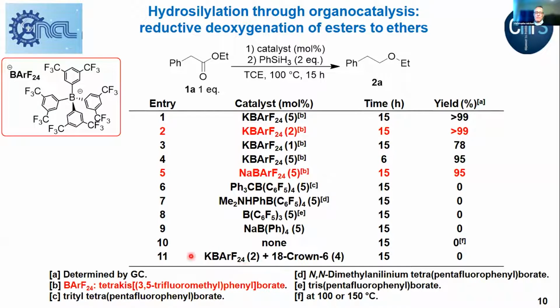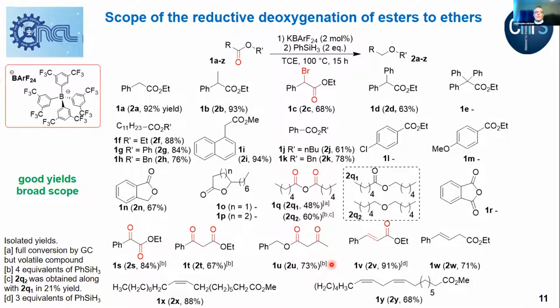We evidenced the key role of the potassium in this reaction by trapping it with 18-crown-6 ether. As a result, the reaction was completely quenched while using this crown ether, which trapped the potassium completely. Looking at the scope of the reductive deoxygenation of esters to ethers, we could evidence a broad reactivity with various alkylated or arylated esters. The reaction has some limitations. Alpha-brominated esters could not be kept; we had debromination while also reducing the carbonyl. Sterically hindered substrates displayed no reactivity, and arylated esters substituted by chloride or methoxy were not reactive at all.